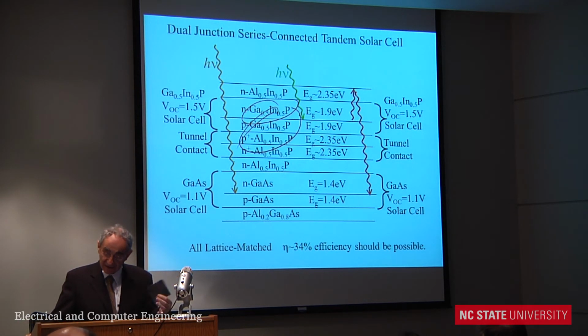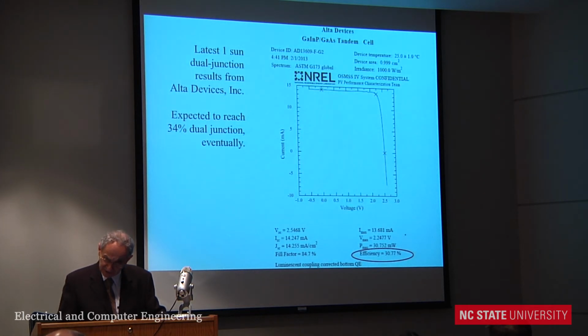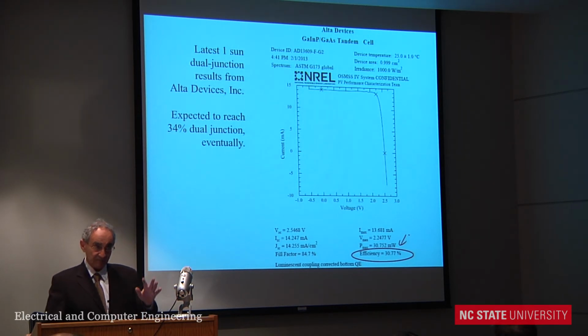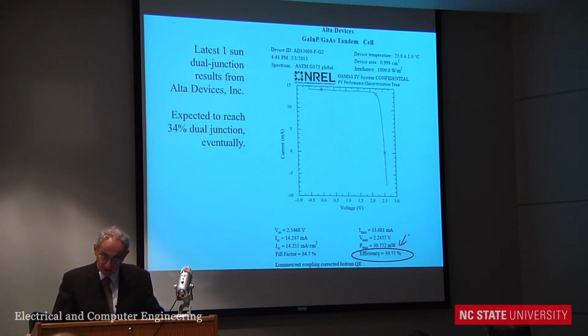You can't tell the difference, except when you send it to be tested by NREL, now there's a new record. So they got up to 30.8% efficiency. They got into the thirties and then they stopped. NREL kept going. NREL, using the same approach, has gone over 31% efficiency. And this approach is capable of maybe 34% efficiency. So from now on, it's all about multi-junctions. This is dual junction. The beauty of this is it's all lattice matched, no added capital equipment. It spends another few seconds in the growth reactor. So over 31%. The CEO said, from now on, unless your efficiency starts with a 3, don't talk to me,